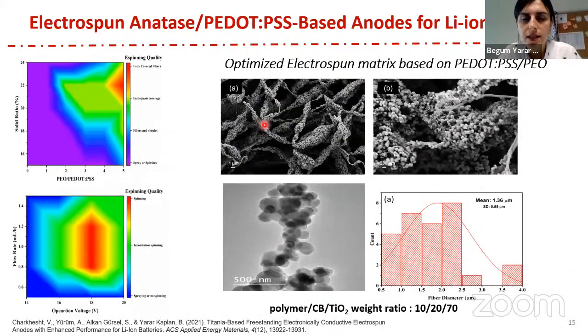and we use this cell for the further tests. So you can see this in the anode study. We use anatase, PEDOT-PSS based materials, and also we use carbon black in this structure. As you can see here, we obtain really good particle distribution along the nanofibers, and really good anatase distribution along these nanofibers. And as you can imagine, it's really hard to obtain these nanofibers. We optimize lots of electrospinning parameters. As you can see here, this red part shows us the optimum conditions for the electrospinning to obtain these nanofiber structures.